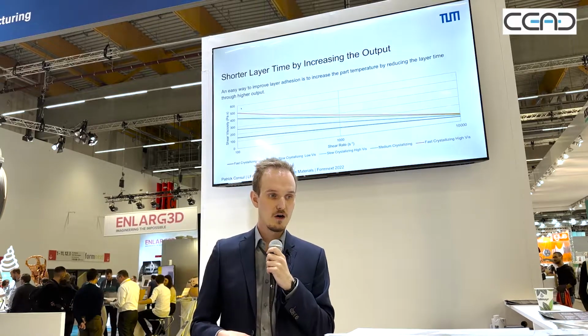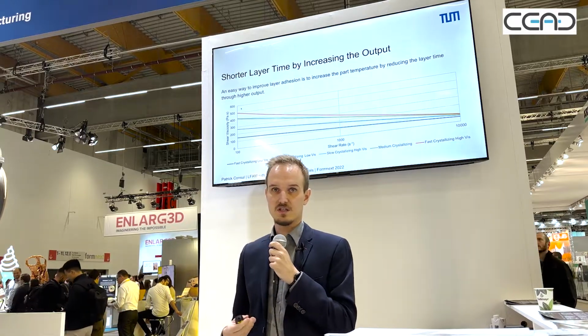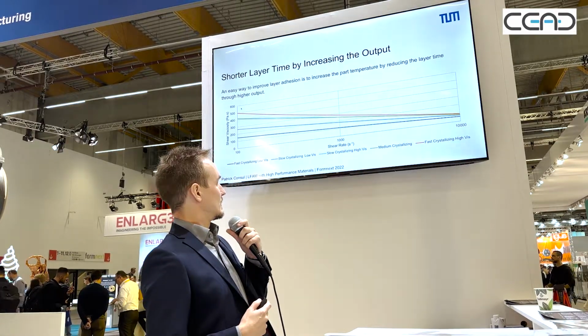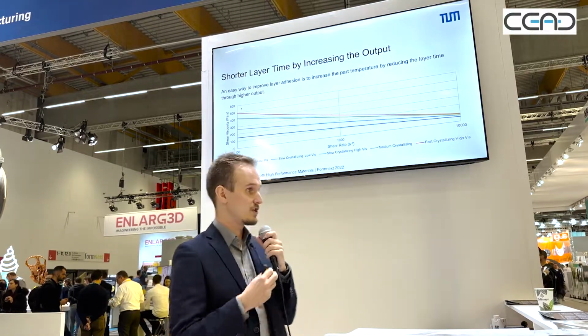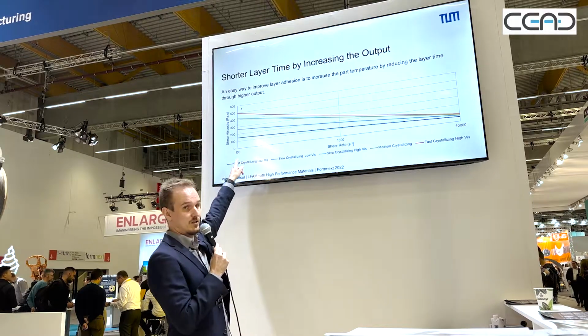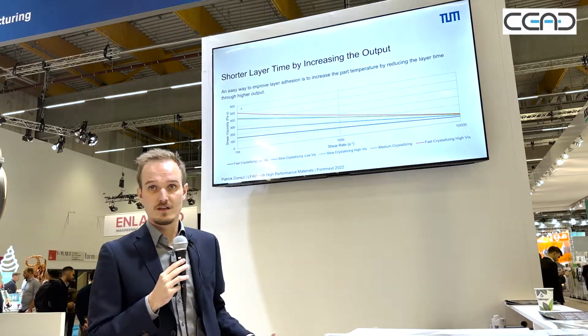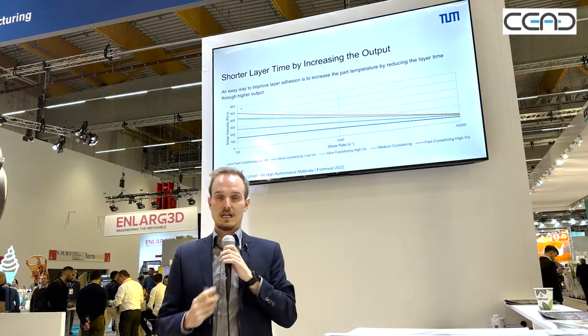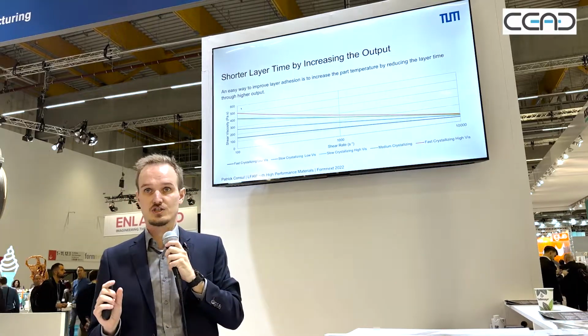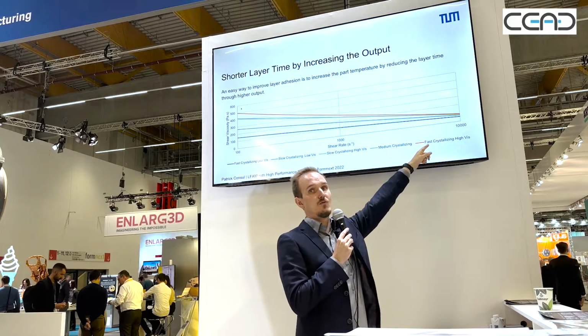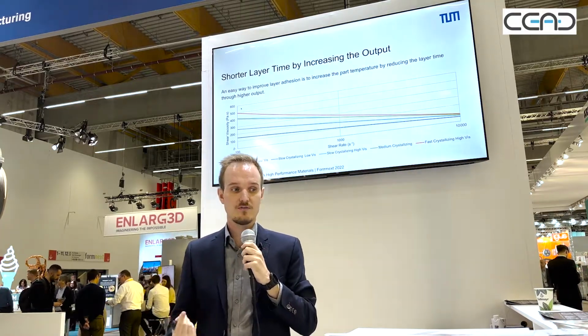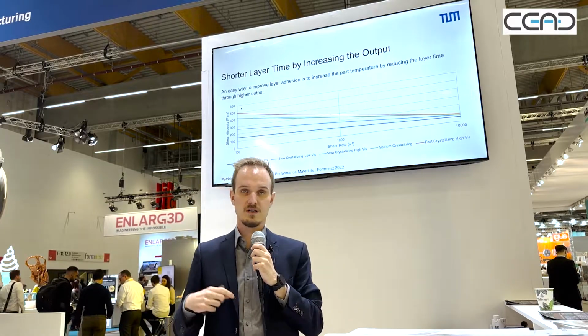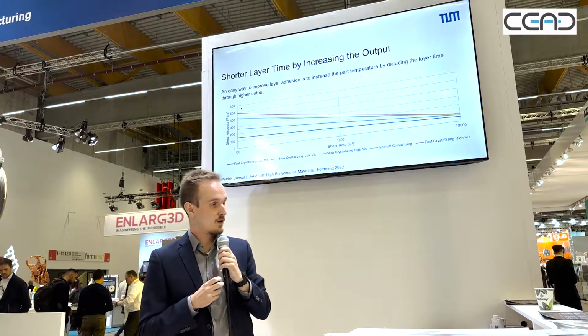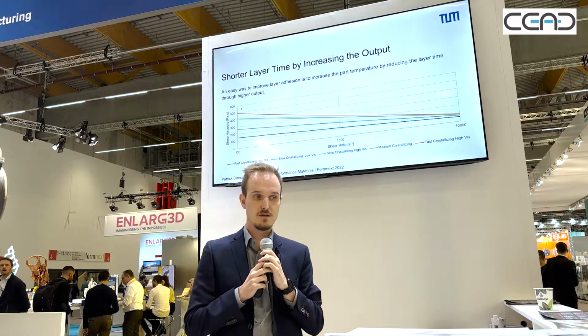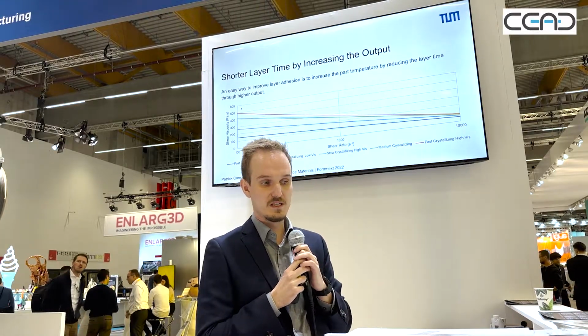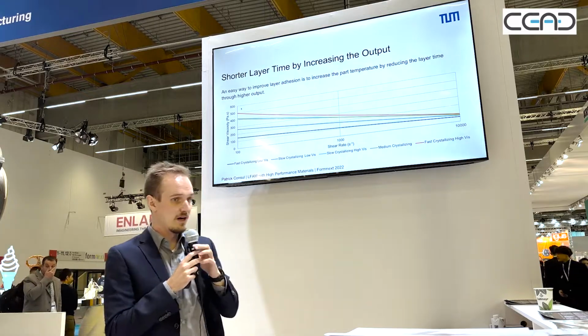So to maximize our output, we started looking at the viscosity of the polymers. And yeah, in 3D printing, the shear rates are actually quite low. So you're usually somewhere on this end of the diagram. In injection molding, you're usually somewhere on that end of the diagram. And if you get a viscosity indication on a data sheet, quite often it's one that you have somewhere over here. And polymers that behave very similarly in injection molding might behave very differently in 3D printing. So we ended up choosing one with a viscosity as low as possible and a crystallization speed as slow as possible. So in our case, it's the blue line.